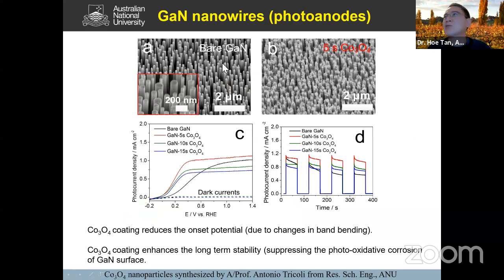So we are using this gallium nitride to make the nanowires. So again, we grow the gallium nitride layer and use the nickel and the silicon dioxide mask technique to make this nanowire. Okay, so just focus on this one first. So we have the bare nanowire. If you look at this plot, this is the photocurrent density as a function of bias. If you look at the black curve, okay, so we do see some onset of the photocurrent when you shine light onto this photoelectrode. Okay, so this is the bare gallium nitride.